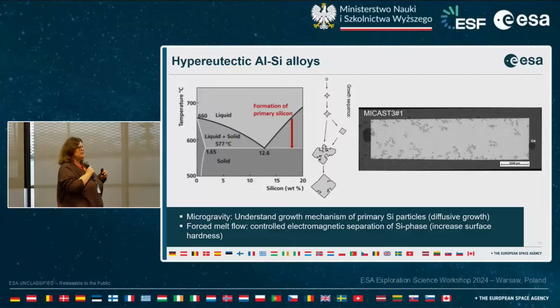On one side, because aluminum and silicon have more or less the same density, the question was: if you solidify such a type of alloy, what happens with the primary silicon phases? Are they floating up, sinking down? We don't know yet. So this was a point where we said, okay, this can be investigated only in microgravity. And the second point is more technology-driven. Can we push, in principle, the primary silicon particles towards the direction we would like to have them? So can we control with electromagnetic methods the separation of the silicon phase, push them to the outer surface of a sample to produce a material with an increased surface hardness?